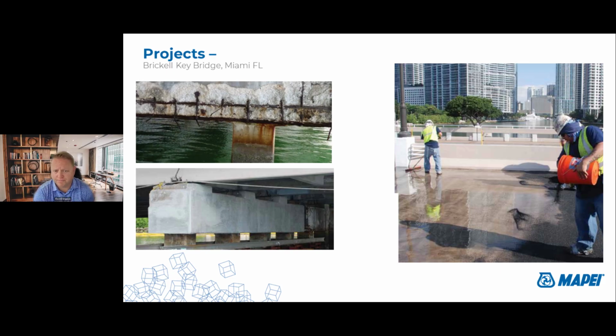So one project down in Miami, Florida, we used several of these different types of products. This is the Brickell Key Bridge. You can see the pile caps here on this bridge. A lot of corrosion. We cleaned those off. We used this Planibond 3C rebar coating on those. And then for the patch material, we used Planitop 15. That's the one that has the fumed silica in it and has corrosion inhibitors. That's sort of designed for these harsher environments. And then for the deck, we used this Planiseal traffic coat. And then you can see this gentleman casting some aggregate in here, a clean quartz sand. There are different types of things you can use to help with that friction.